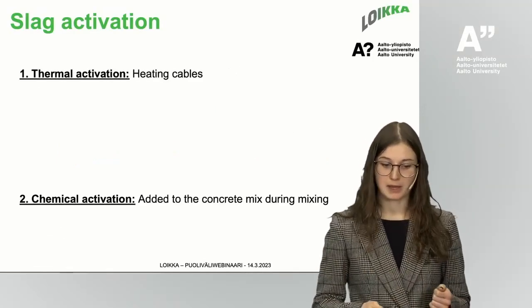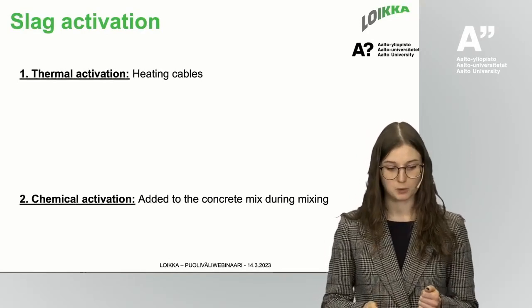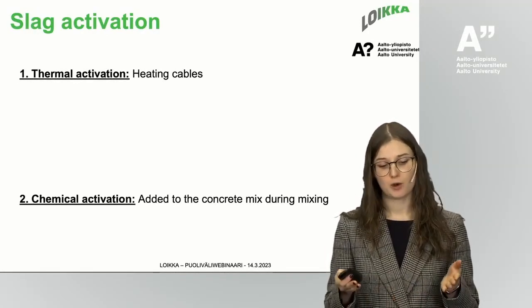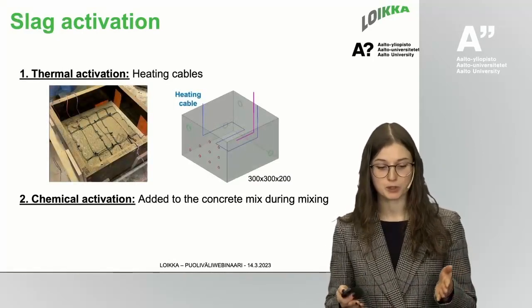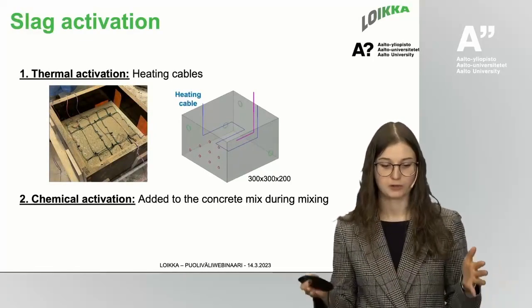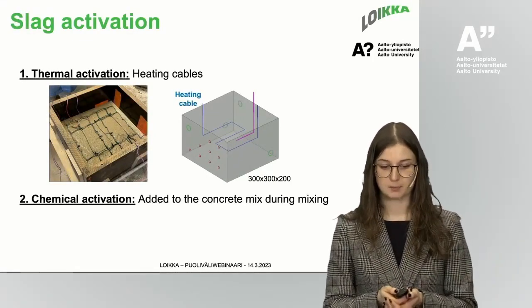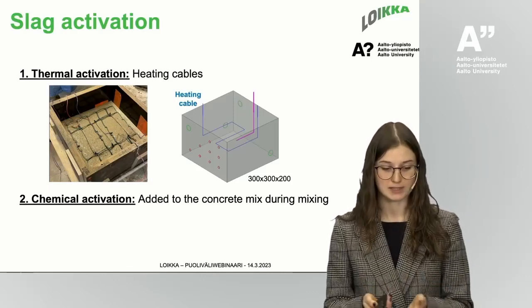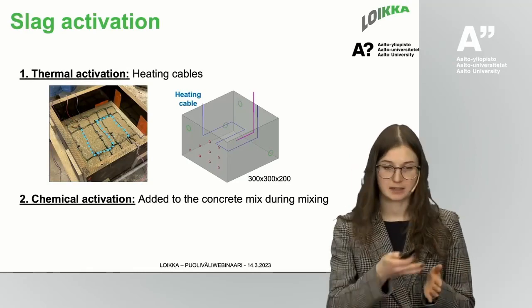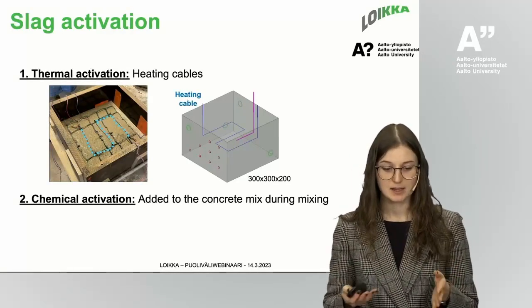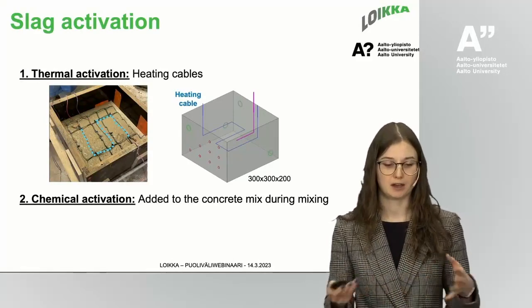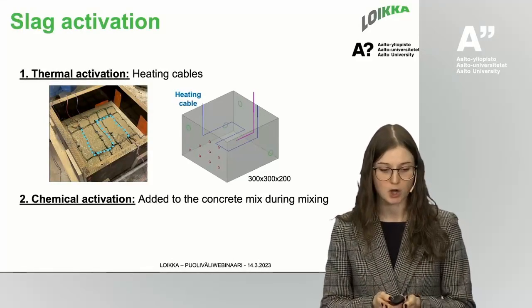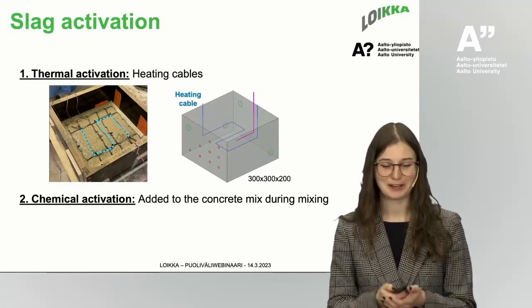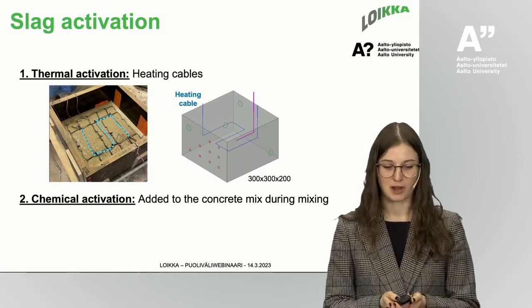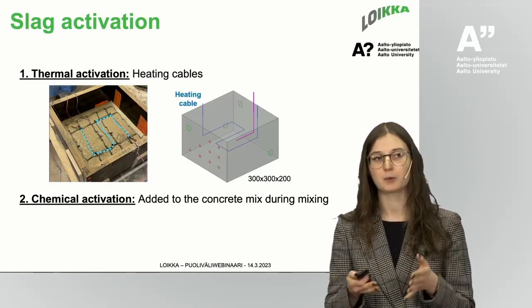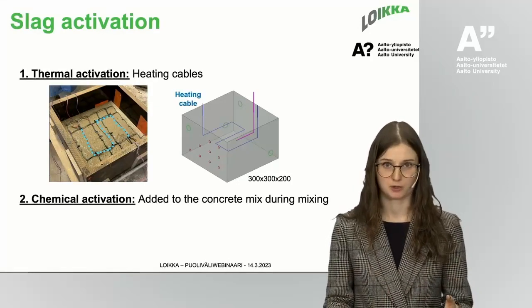I will explain a bit about those activation methods. First of all, for the thermal activation, we implemented heating cables, which were cast in the middle of the concrete samples with the cement binders that I mentioned before, with a high content of slag. They were placed in a loop pattern, similar to the one used for heating concrete in low temperatures, usually during winter time, even though it's not that popular right now, maybe. But we still wanted to try this method because we can control the amount of power, the amount of heat, we're giving into the system.